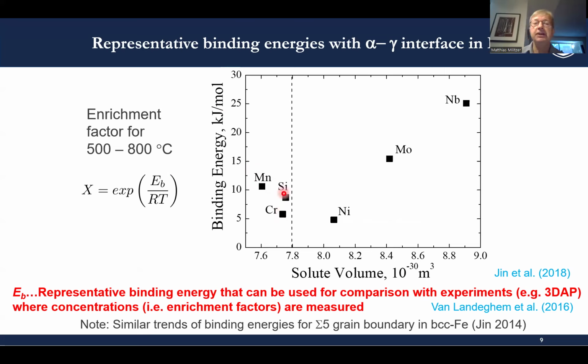So silicon has a very different electronic structure than the transition metals. Manganese and chromium prefer an antiferromagnetic ordering, and so they may see something that we call magnetic frustration in an otherwise ferromagnetic system. What is important to realize is that the enrichment factor that we predict can be compared with experimental data from 3D atom probe studies, where we can translate the measured concentrations back into a representative binding energy. We did this for a study that was done a number of years ago by Van Landeghem, for a number of these alloying elements.